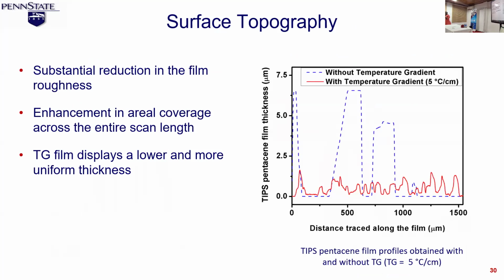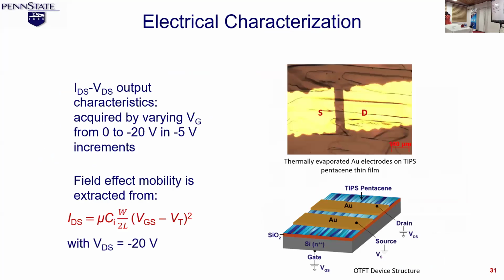Right. This just shows an image of the surface roughness of the crystals. The blue dashed line is without temperature gradient. You notice how rough that surface is, because every valley is essentially the substrate surface, and every peak is a crystal. And then the red line is the one with the temperature gradient method using 5 degrees Celsius per centimeter. Again, showing an improvement.